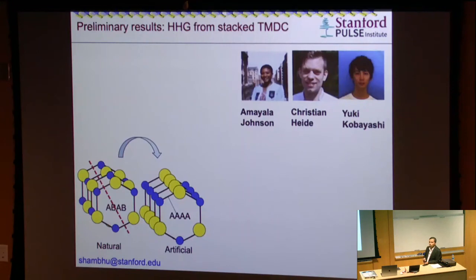So how are you physically in the lab actually doing that delamination? Yeah, that was the second question from my daughter. She's a 7th grader, so I had a hard time explaining. But what I told her was that I take the Scotch tape and then just stick it and then put it there. Of course, this is not exactly what happens, but the idea is the same. They use gold tape. They exfoliate on the gold tape, and there is some cleaning procedure. You need to get rid of the gold and all that. But it's a really interesting process. So you have a way now to arrange these layers however you like.